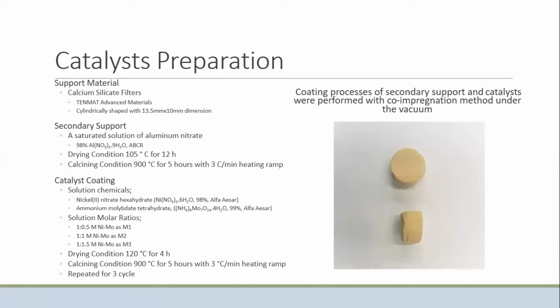In the preparation of the catalyst, different molar ratios of nickel and molybdenum solution were coated on button-shaped calcium silicate filter, which was previously coated with aluminum. After drying and calcining, the coating process was repeated for 3 cycles. The coating of the secondary support and catalyst was performed with the co-impregnation method under vacuum.